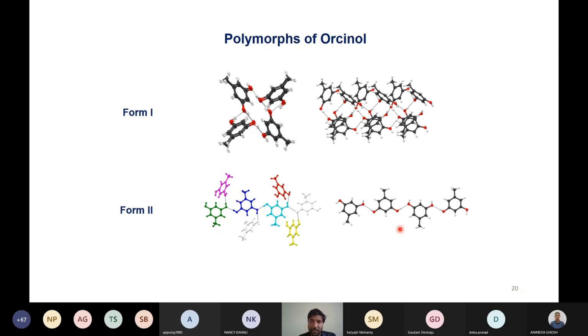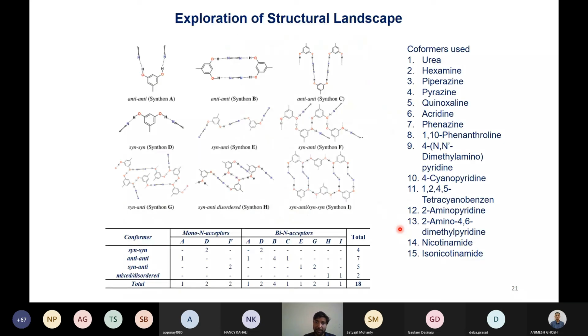Also, we obtained polymorphs of orcinol, where form 1 was a Z-prime 1 structure, but form 2 was a Z-prime 8 structure, where 8 molecules with different conformations are incorporated in the asymmetric unit. So that tells us this could be a suitable system to study this problem. When we tried to co-crystallize it with different co-formers, mostly pyridine based but with still some diversity, we saw that in many cases there was very specific binding between a particular conformer of orcinol and the co-former. So it again illustrates that co-crystallization can be used as a separation technique for impurity and target compounds, as well as different conformers possible in the API molecules.